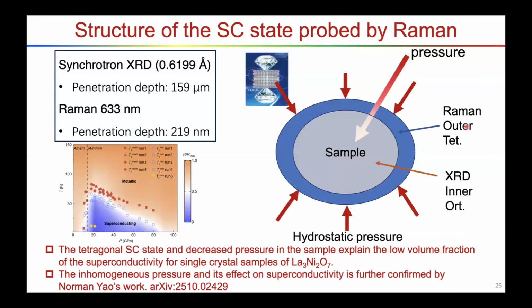Raman only measures the outer shell of the sample. It's tetragonal because the pressure is higher. X-ray diffraction measures the average of the whole sample, or the inner side of the sample. So it's orthorhombic because the pressure is decreased on the inner side of the sample. This picture can also explain why the superconducting volume fraction is low for single crystal samples.